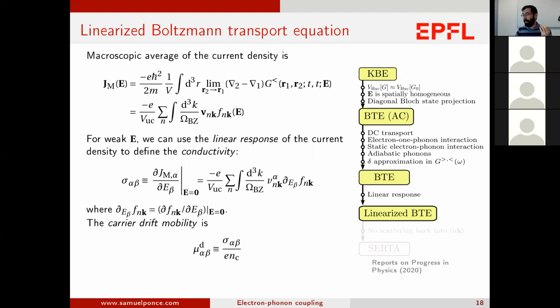In a semiconductor or an insulator, if you prepare a sample, sometimes experimentally it's difficult to know exactly the carrier concentration. And even if you do, it means that you have one value for each sample. For each sample, you will have a different amount of charge, and therefore a different conductivity. Whereas if you divide by the carrier concentration, then you have an intrinsic property that only depends on the material. And so regardless of the sample, you will always get the same mobility.